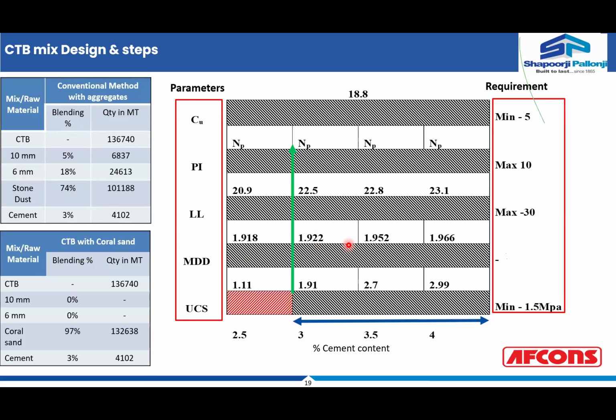So that gives you an indication that in the absence of the coral sand, you are able to achieve 20% PI, but with coral sand, you are able to increase your PI values with the increase in the cement content. So this is the table which gives you the idea that even if you replace the naturally available aggregate, that is 10 mm, 6 mm and stone dust, in this particular place with complete coral sand, the engineering parameters are not changed or compromised, and you are able to achieve the required values. So those things can be produced and used in the field.